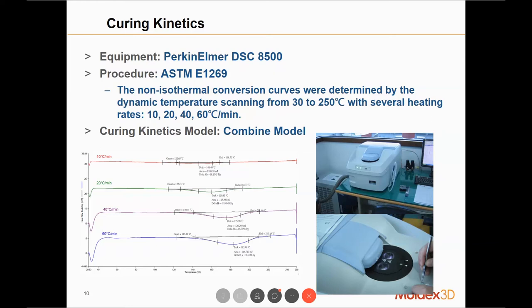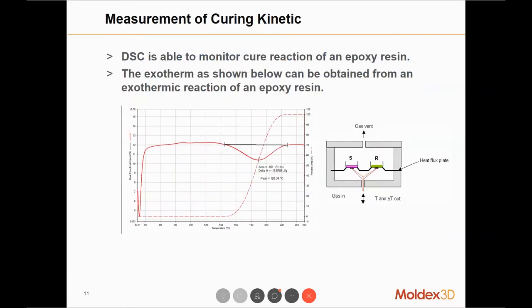So for curing kinetics, we can use the DSC 8500 with the procedure ASTM E1269. We will perform the test under four different heating rates, from 10 to 20, 40, and 60 degrees Celsius per minute, and we'll heat up the material from 30 degrees to 250 degrees Celsius. So let's go to the next page first to look at what exactly it looks like.